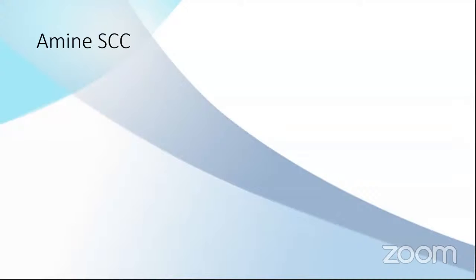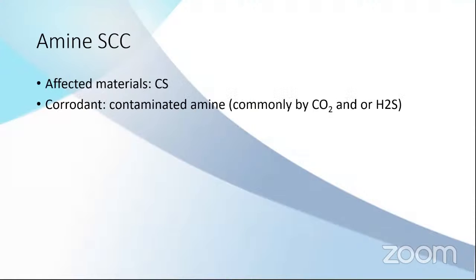Another form of cracking is amine stress corrosion cracking, but this only happens to carbon steel. The corrodant is contaminated amine. Most of the time it is contaminated by carbon dioxide or H2S. And normally this is also in oil and gas. This is used for gas treating. They treat the gas to take out the CO2 and H2S so they can sell the gas like LPG or LNG.